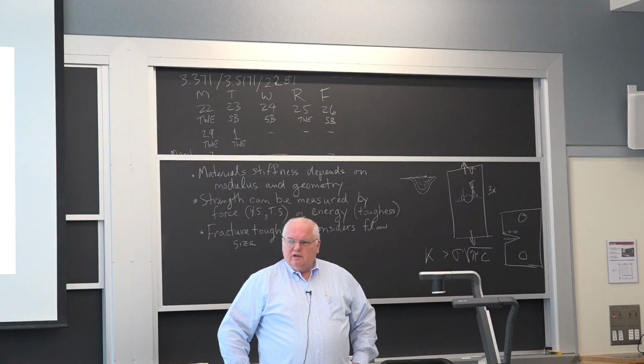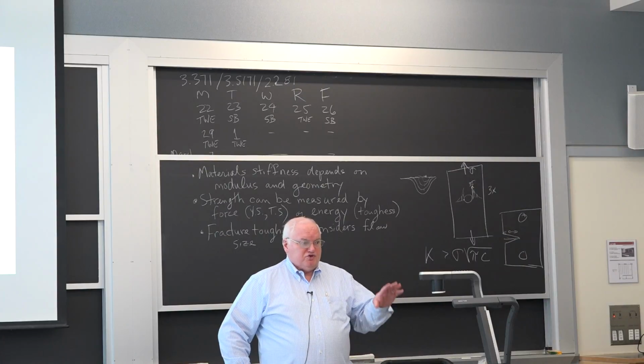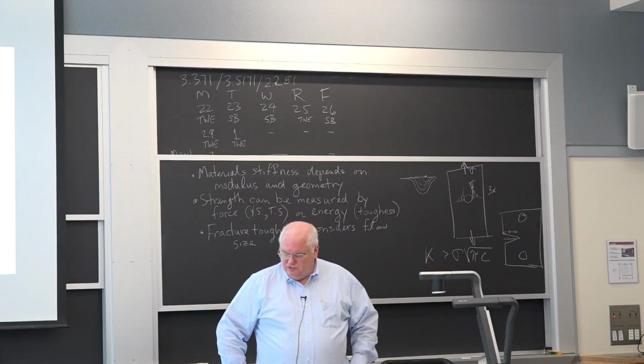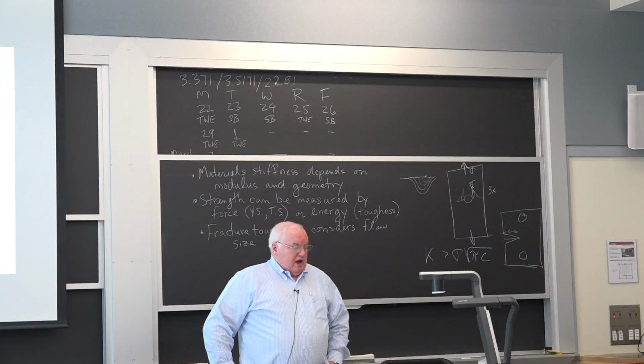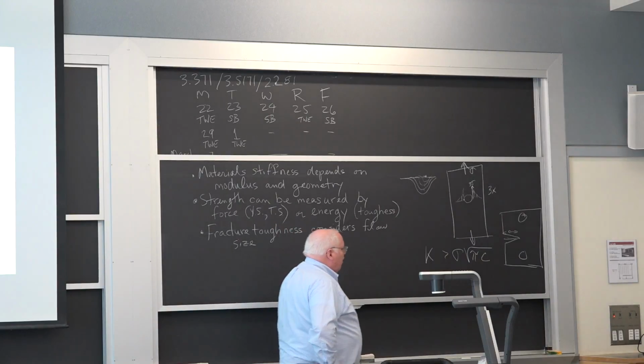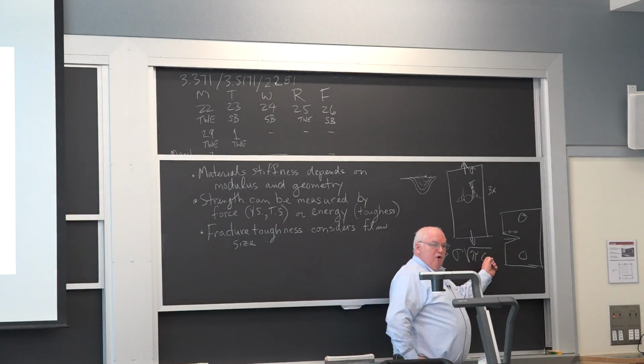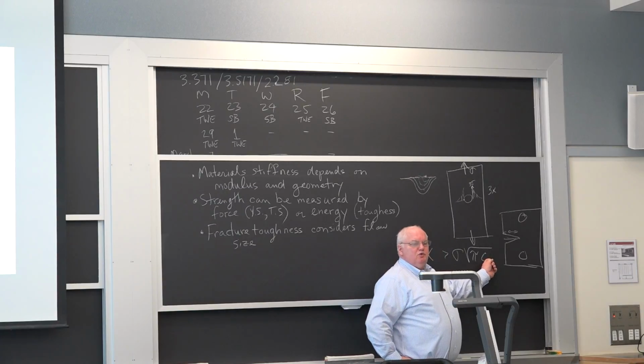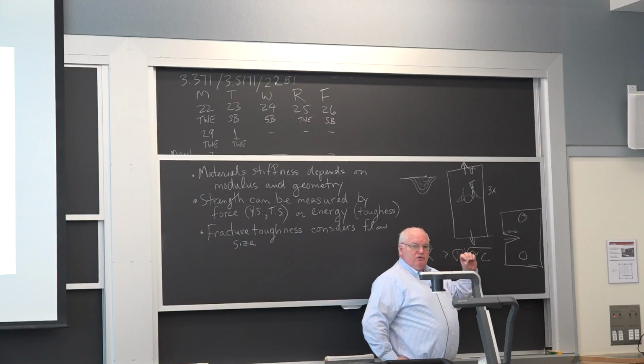But we had 700 of these around the world. And the question was, how do you inspect them? It turns out the critical flaw size for that was no more than 2 millimeters in size. If you measure the toughness of that improperly heat-treated steel, and you calculate what size flaw, just like a small flaw in glass, will cause you to lose all your strength: in this case, less than a 2 millimeter flaw in one of these drilled holes.